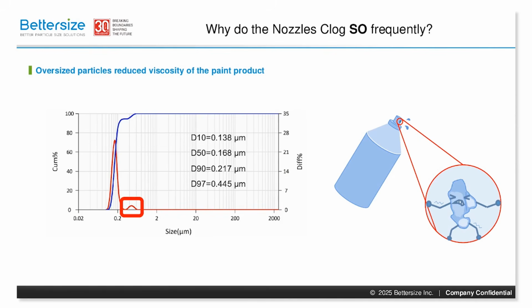The animation on the right shows how agglomerates clog nozzles, leading to spray paint failure. The Bettersize 2600 helped this paint provider identify and quantify these oversized particles, allowing them to adjust their process and solve the problem with an optimized grinding setup and finer filtration.